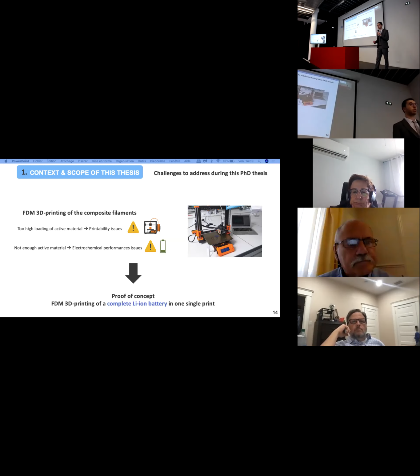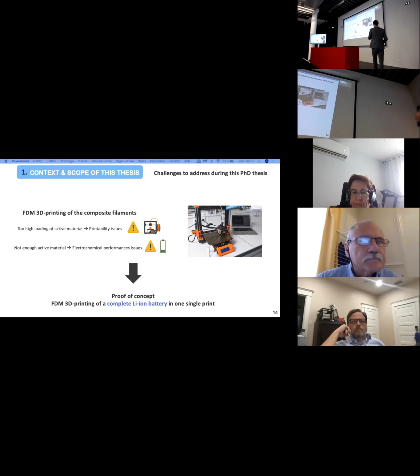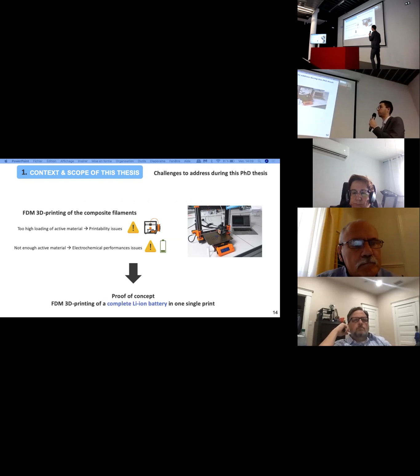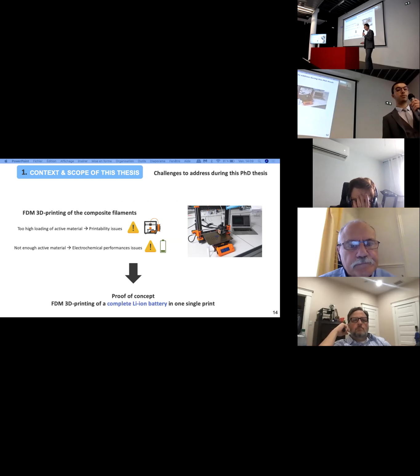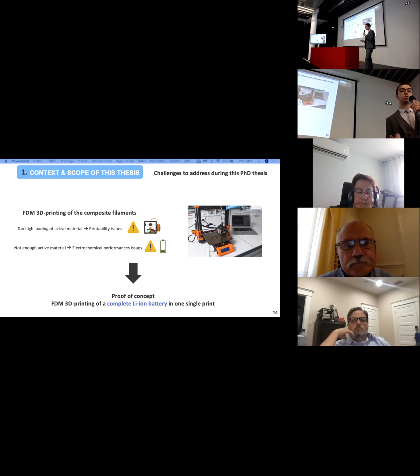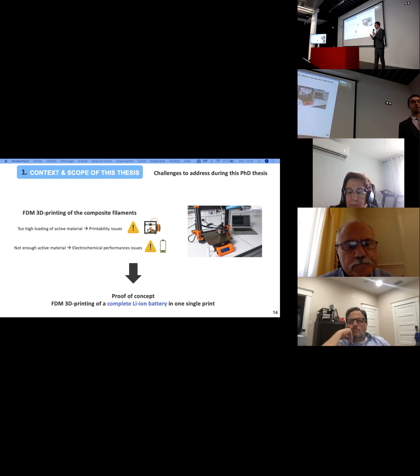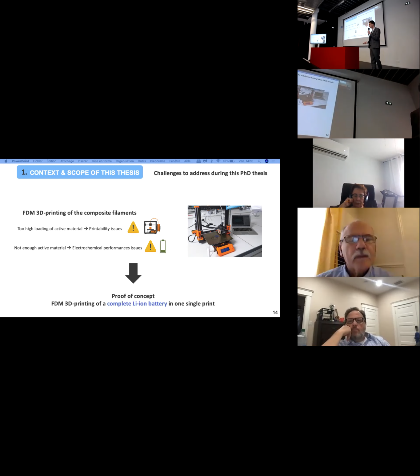Of course, it was a huge compromise that we needed to make between the mechanical performances on one side and the electrochemical performances on the other. If you have a filament with too high a loading of active material, you will clearly have some printability issues. While on the contrary, if you don't have enough active material within your filament, then what you are able to print will show poor electrochemical performance. So that was really a huge compromise. Finally, once we finished developing these filaments, the main goal of this PhD thesis was to print the complete lithium-ion battery in one single step. That was the main goal.